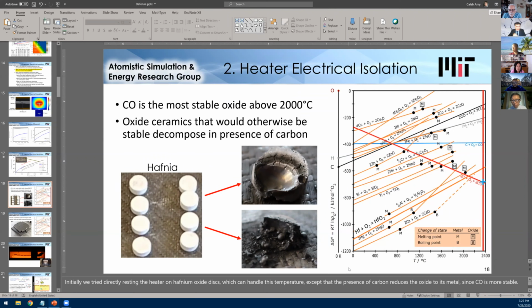So because there's no reaction, the point of change between carbon and tin would be the failure of carbon itself, which is by sublimation at 3,000 something, 4,000, quite hot, high 3,000s. So that's why tin is much better. There's not really any other metal or cheap material that you can use. One alternative we considered for a while was maybe pumping a liquid oxide like alumina or silica, because these are cheap materials. But the problem is they have oxygen, and the carbon will pull the oxygen out and become a gas, and the wall will disappear.